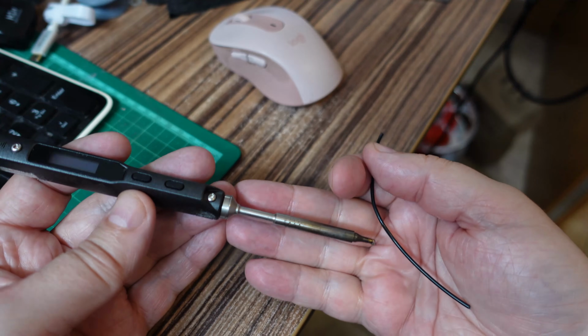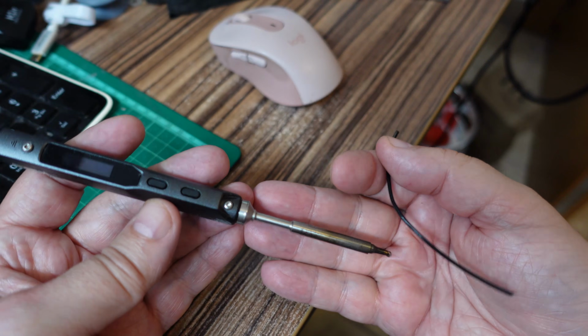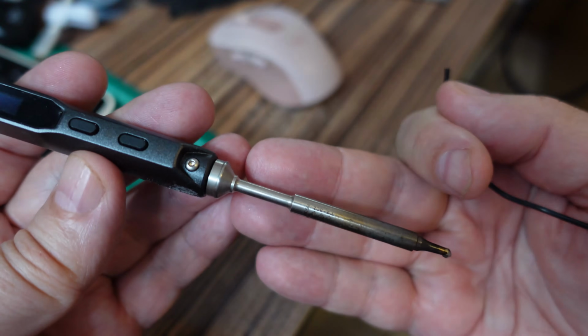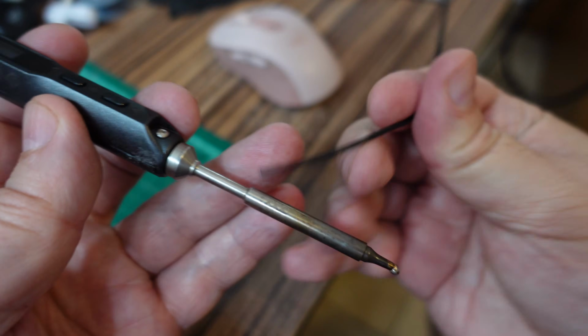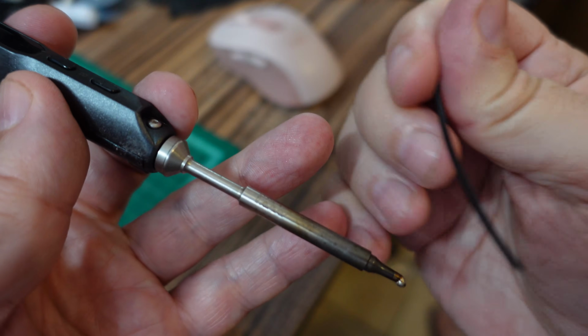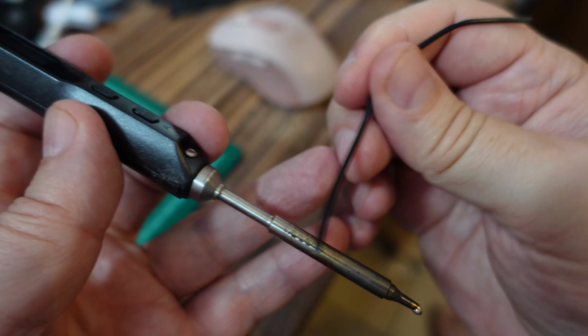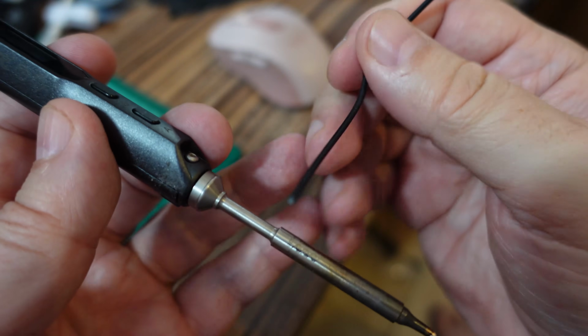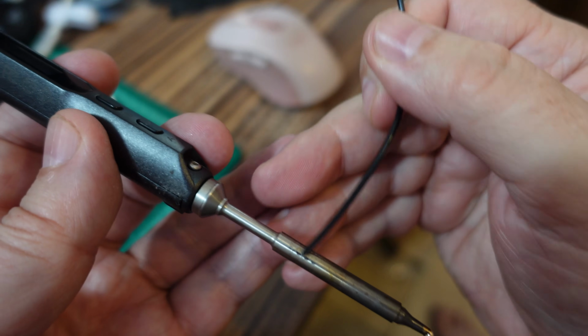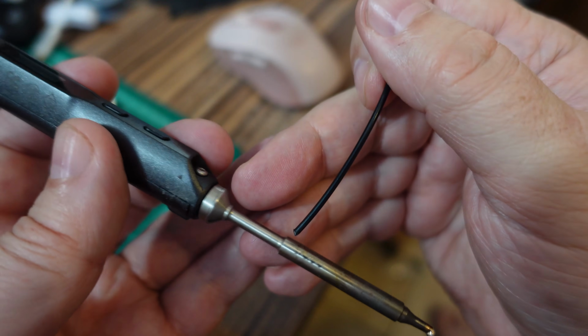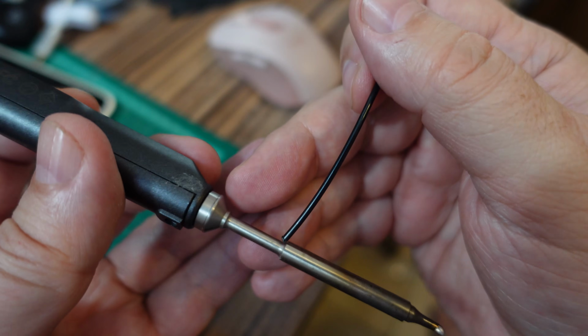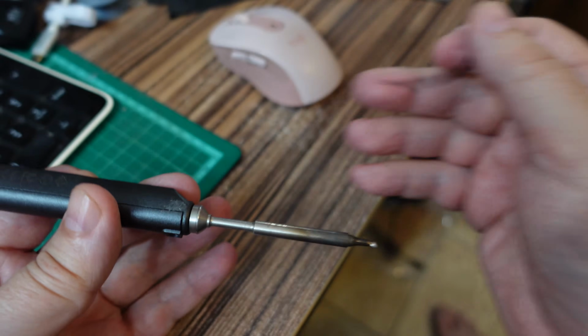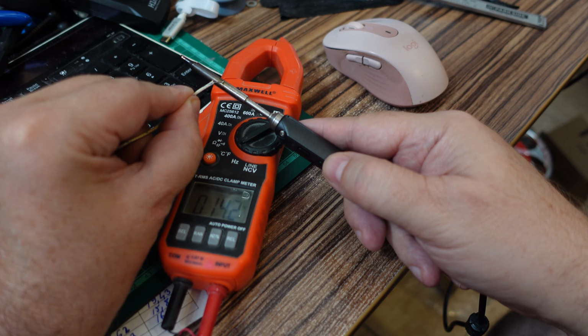This is my soldering iron and I don't have the rest for it, and I'm very curious if PPS-CF will survive these temperatures. I can see from color transition that here we have much higher temperatures and here there is no color change, and maybe if I use only this area as a support then it should be fine, just for curiosity. Let's measure the temperatures. Looks like it will be around 150 degrees Celsius.